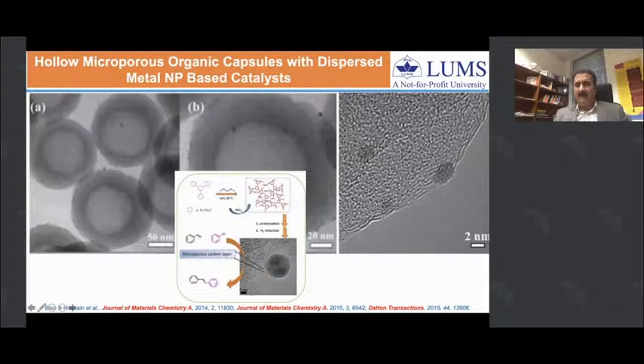Apart from this, we also generated these kind of metal nanoclusters of palladium and platinum in microporous hollow capsules. By confining these metal precursors in the smaller pores of these polymers, we were able to produce very small clusters in these polymeric capsules that were catalytically active for Suzuki coupling reaction.